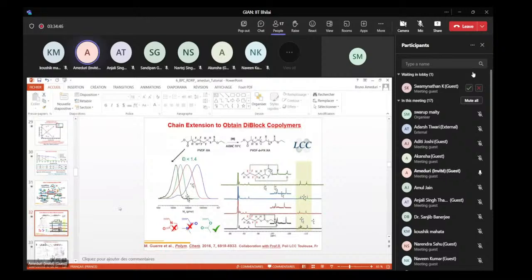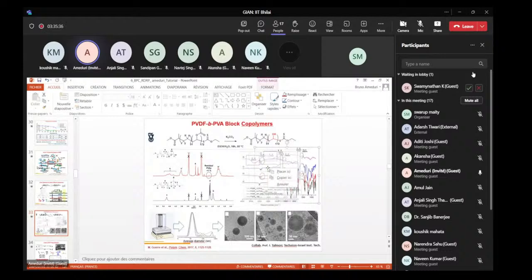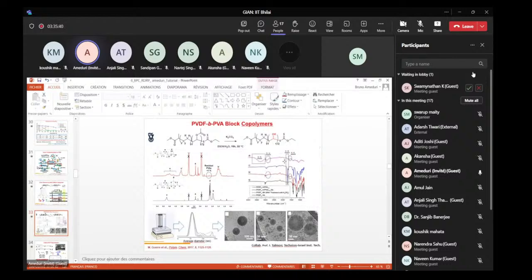So this was very interesting, and we wanted to go a little bit further to carry out the hydrolysis, because polyvinyl acetate is hydrophobic, however, if you are able to hydrolyze it into vinyl alcohol, this gives a hydrophilic sequence. And this was well identified by NMR. When you look at the polyvinyl acetate moiety, after hydrolysis you lose the characteristic CH3 of the acetate. And even by IR, this is the PVDF-acetate, and after reaction, the polyvinyl alcohol shows the presence of OH and the vanishing of the carbonyl of vinyl acetate. So it was very interesting to evidence by both techniques that we had hydrolyzed the vinyl acetate into vinyl alcohol.